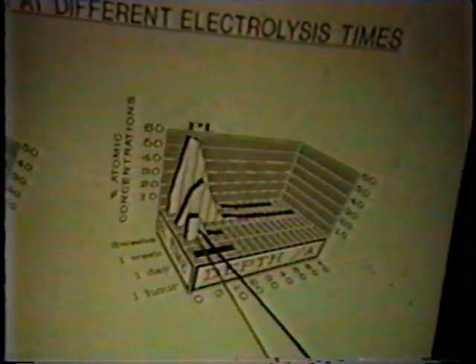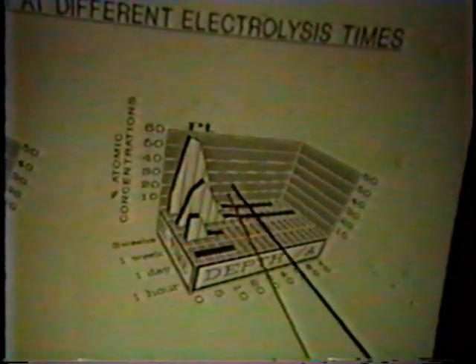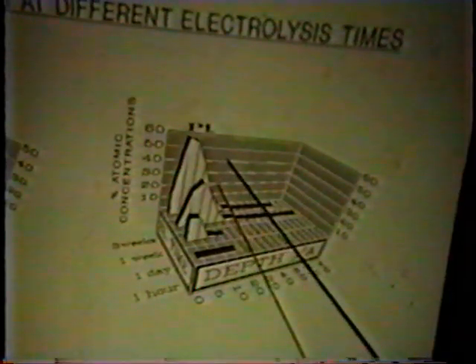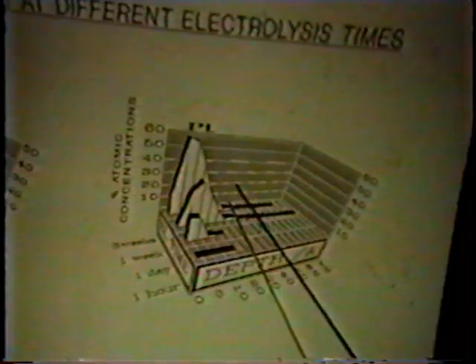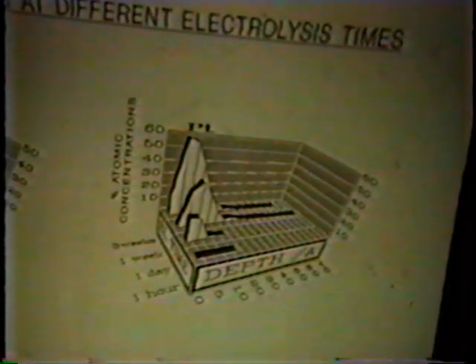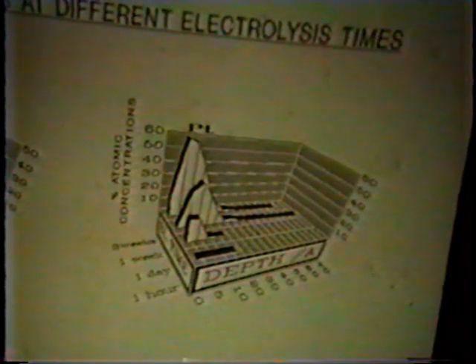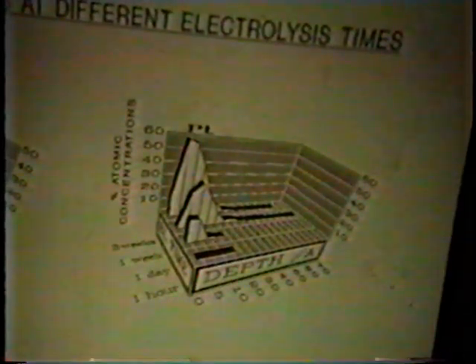So you can't see much after an hour, but after a day, it's already up to 10% coverage. And after 3 weeks, 60% of the surface is covered with platinum. And then down to a depth of about 10 angstroms, almost the same, falls off exponentially, but you can still get registrations of the platinum with XPS through 70 or 80 angstroms. So you see, there's the first real solid evidence we've got on all the platinum there.